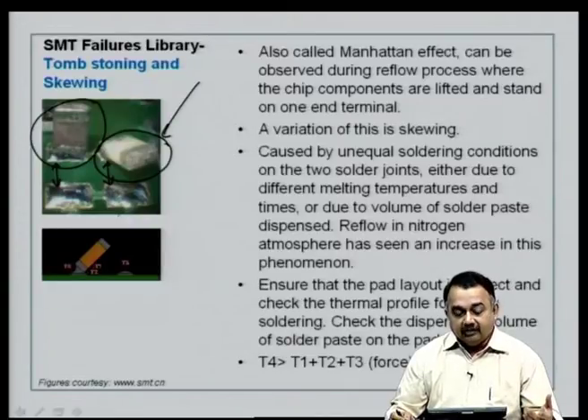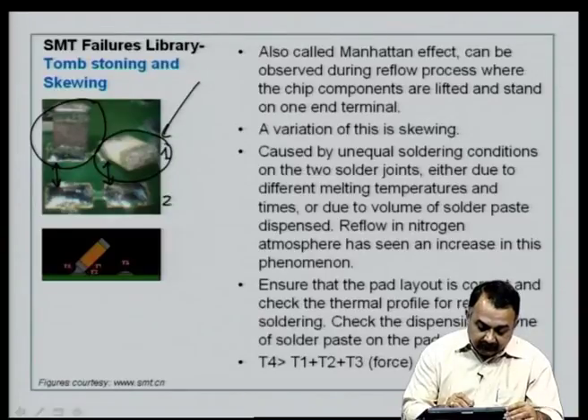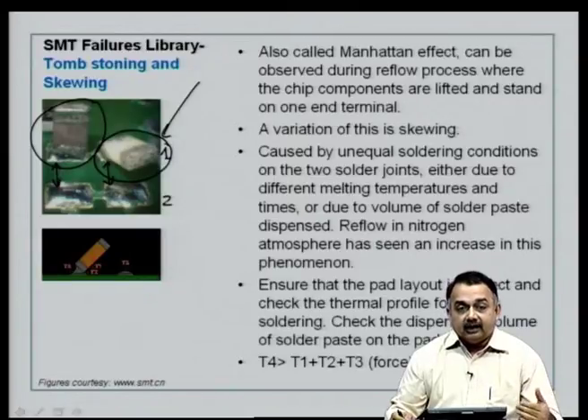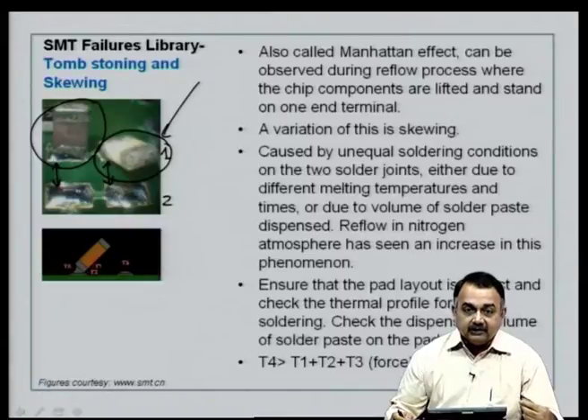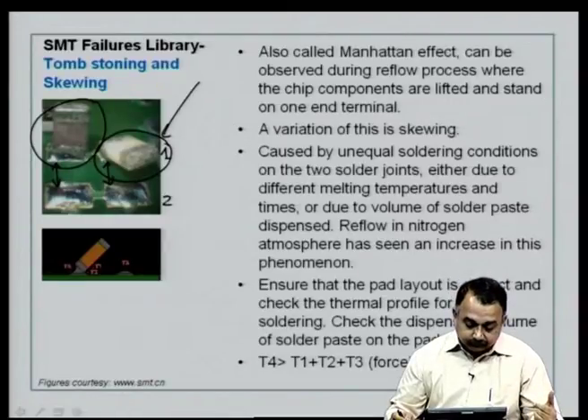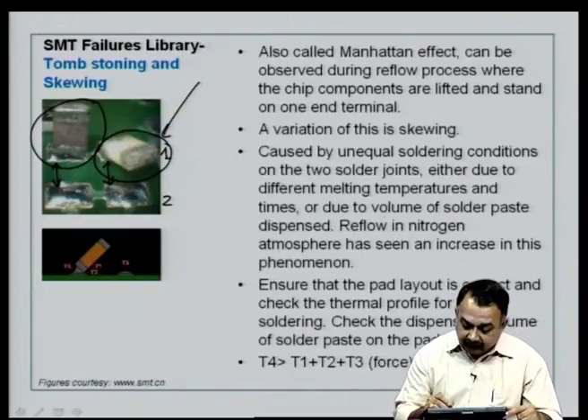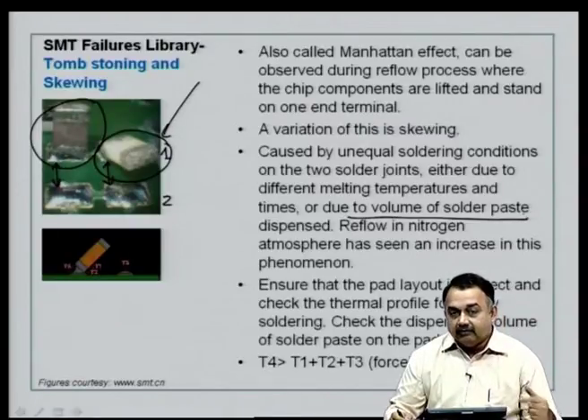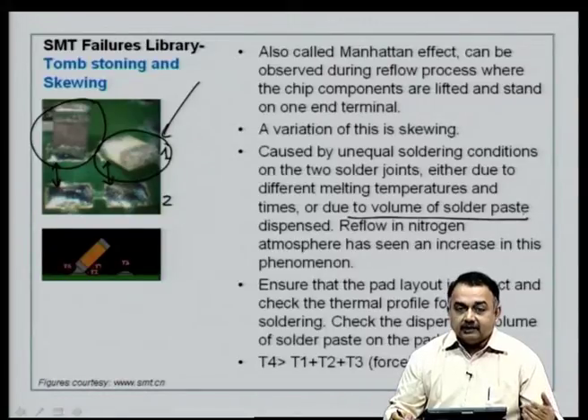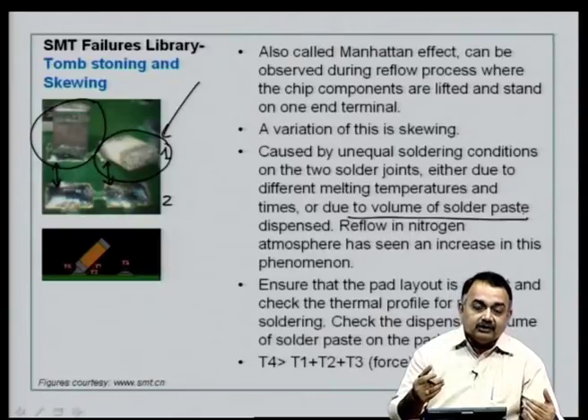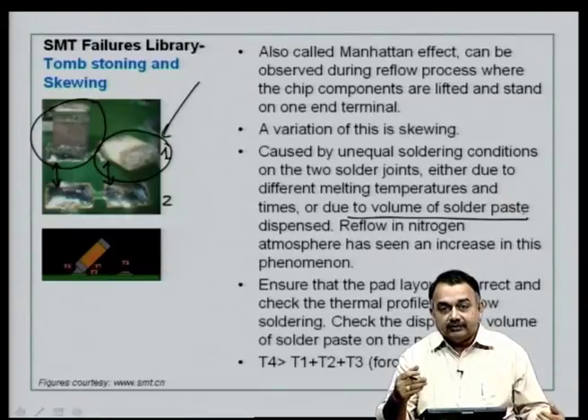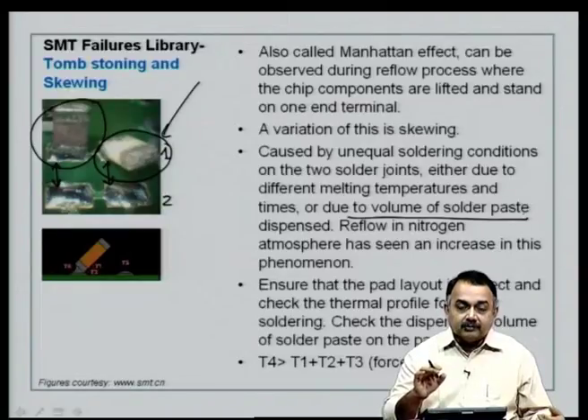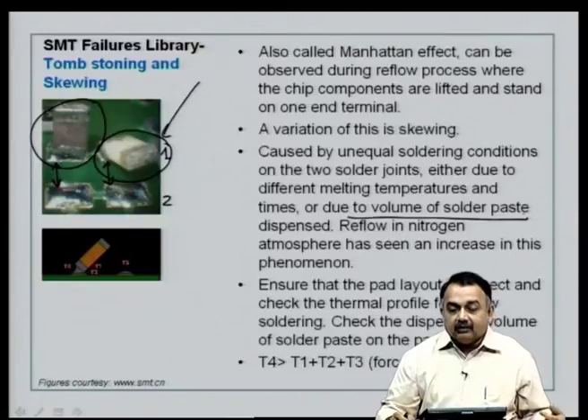This has happened either due to different melting temperatures on, let us say, pad 1 and pad 2, and also different times that you have given for the reflow process, or the time taken for the solder material that you have dispensed on the board to melt. This time has been unequal on the different pads. Now, this could also be due to different volume of solder paste that you have dispensed. Now, if you recall, solder paste is dispensed either by syringe dispensing. For small prototyping you can do it manually, and that is where the problem comes. If you do manual solder paste dispense using a syringe, you tend to have unequal volumes on the pad, and therefore, these kinds of problems typically occur when you do manual syringe dispensing of the solder paste.